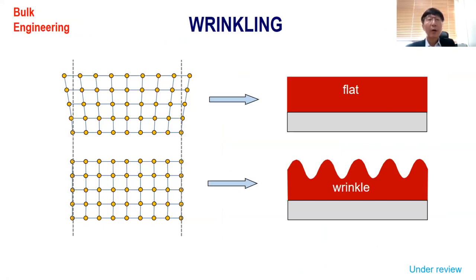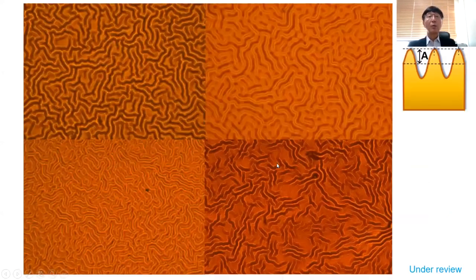So for bulk engineering, usually a flat surface may be better to contact the hole transporting layer. However, we found from the optical simulation that the wrinkle structure is better than a flat surface. Usually, the flat surface comes from some kind of tension on the surface of the perovskite film. If you have some compressive strain, then you can have the wrinkle structure.